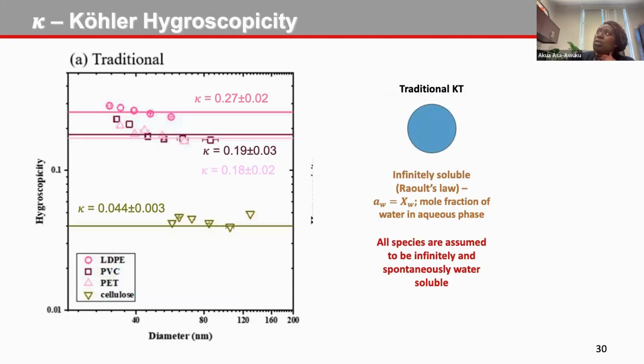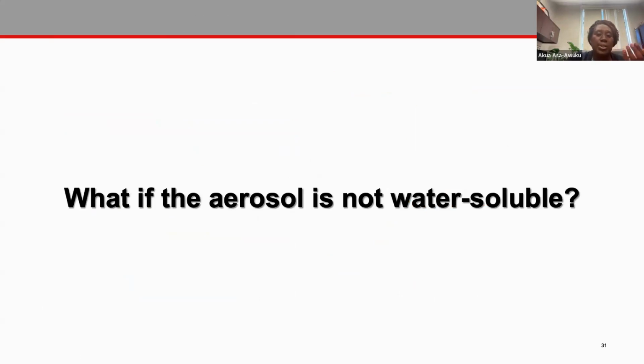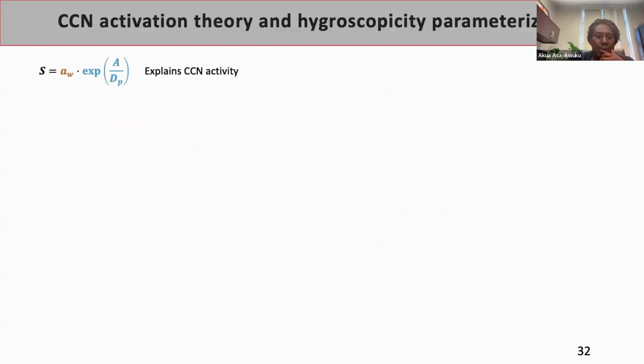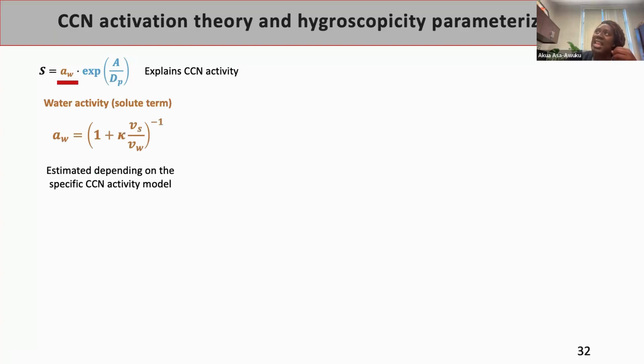So again, I mentioned traditional Köhler theory assumes that the aerosol itself dissolves and contributes to the droplet growth. But what if the aerosol is not water soluble? What do we use? Well, we actually have some models to help explain this. To understand how the models work, we need to understand the basics of droplet growth again. That is, the supersaturation is a function of what we call the water activity, which describes the interactions of the solute with the water. And that is what drives its hygroscopicity. Petters and Kreidenweis 2007 provided this parameterization based on this kappa value and the molar volume of the solute and water as a parameterization for water activity.